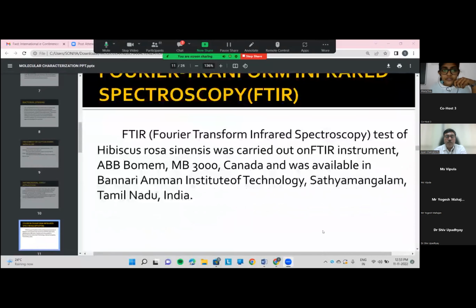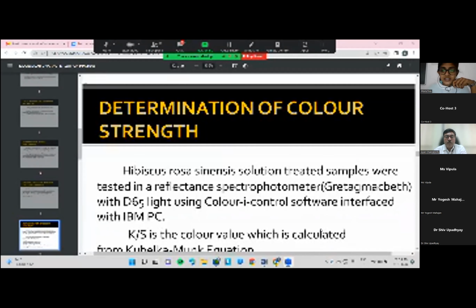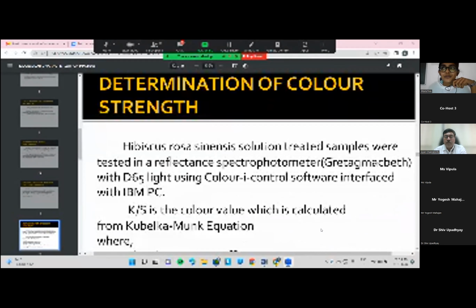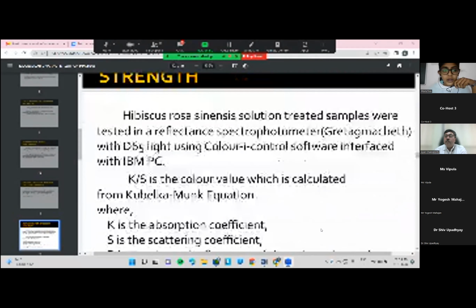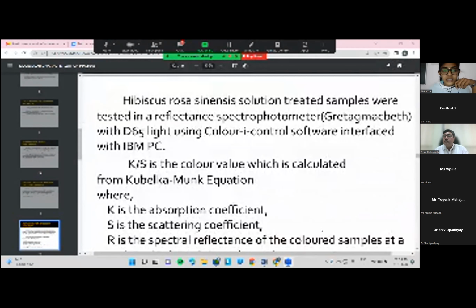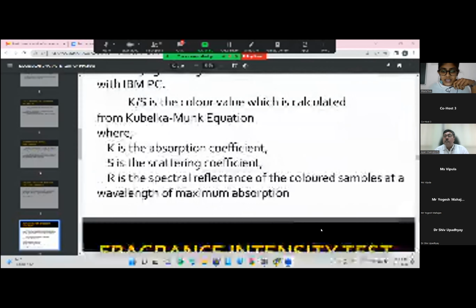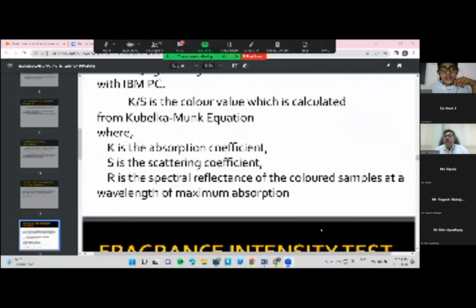Determination of color strength. Hibiscus rosa-sinensis solution treated samples were tested in a reflectance spectrophotometer with D65 light using the Colour-i-control software interface with an IBM PC. K/S is the color value calculated from the Kubelka-Munk equation, where K is the absorption coefficient, S is the scattering coefficient, and R is the spectral reflectance of the colored samples at the wavelength of maximum absorption.